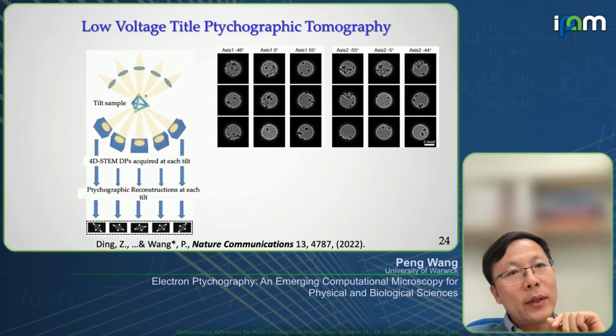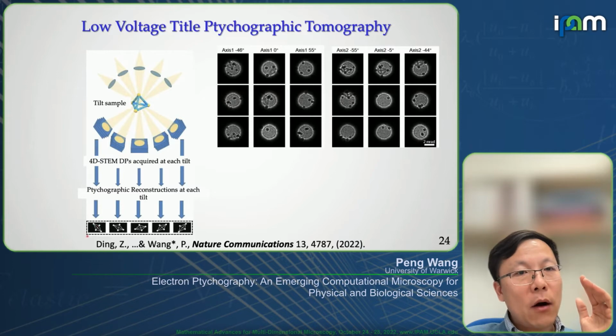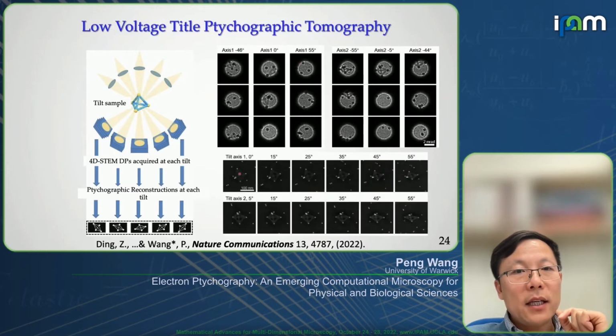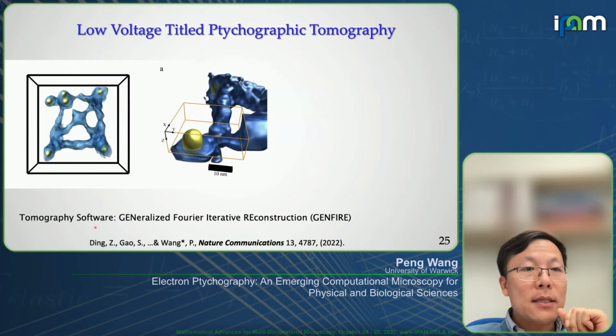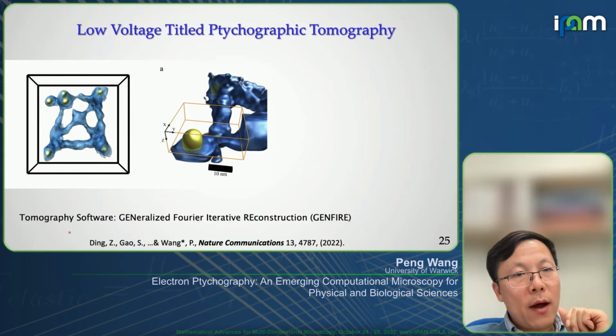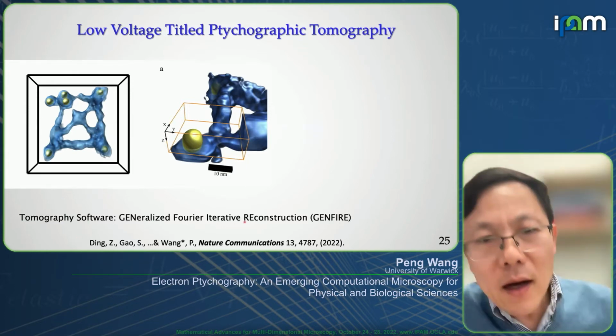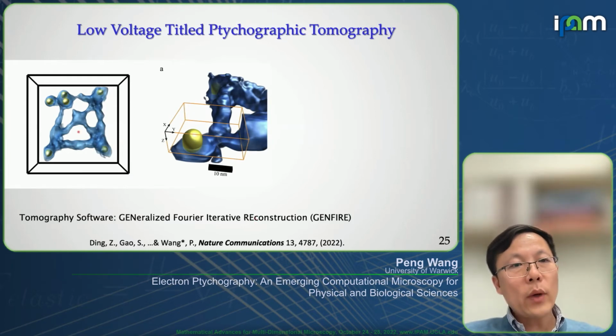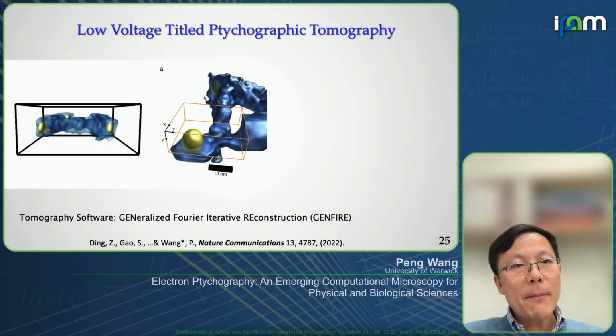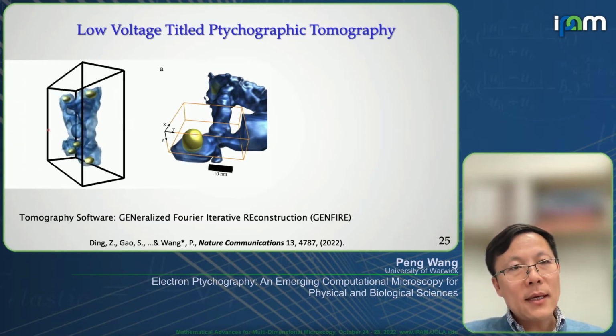So in this type of material, we take a 4D data set at each angle, and then we perform ptychography reconstruction for each angle, and we have a two-dimensional phase image for that angle as a projection. Then we tilt along different angles in two axes, and we can reconstruct each axis with different angles in terms of phase images. And we use current state-of-the-art tomography software, GENFIRE, developed by John Miao's group at UCLA, and we are able to reconstruct this three-dimensional image of DNA origami with the gold particle